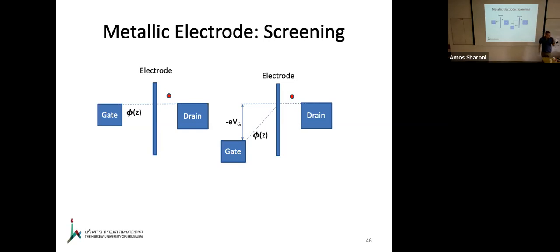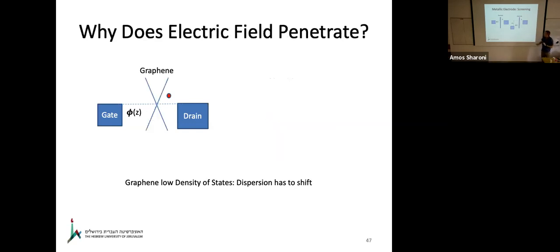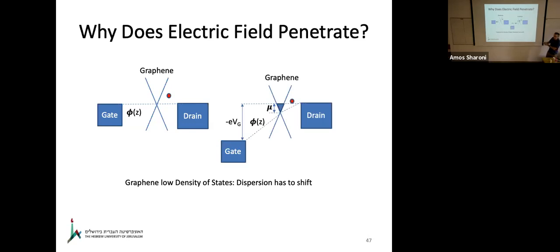Graphene is a very, very poor screener. The reason is that if you apply voltage on a gate, it charges the graphene, pulls down the electrical potential, and creates a chemical potential. So phi plus mu is V, and V, the voltage, stays zero. So you can tune this dot energy up and down and switch the transport on and off. Basically, this means if you have a finite capacitance through graphene, you can actually measure this capacitance.